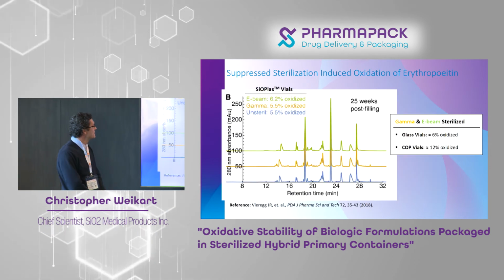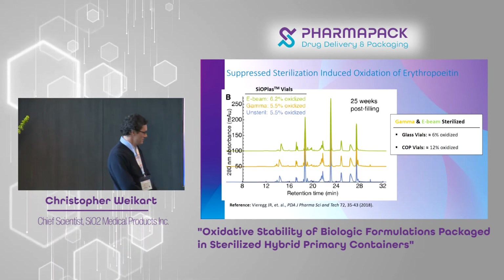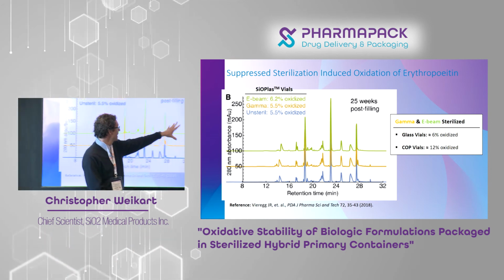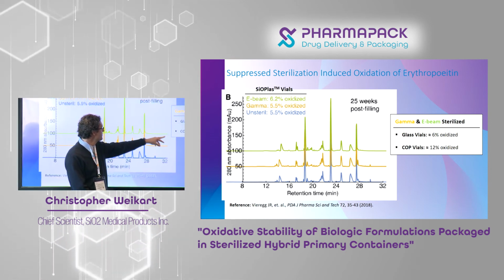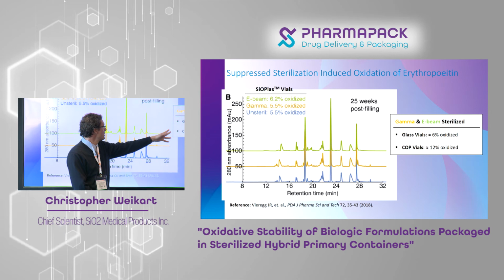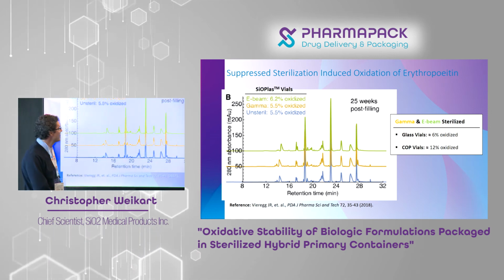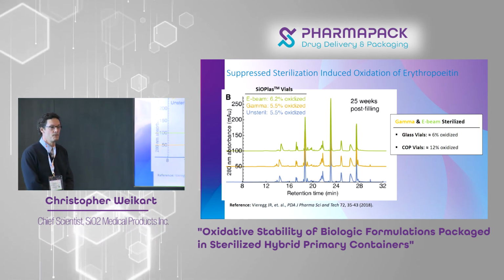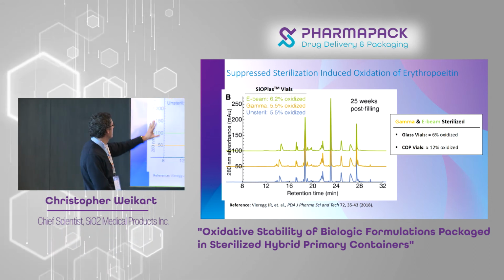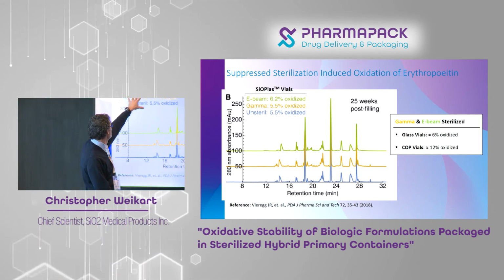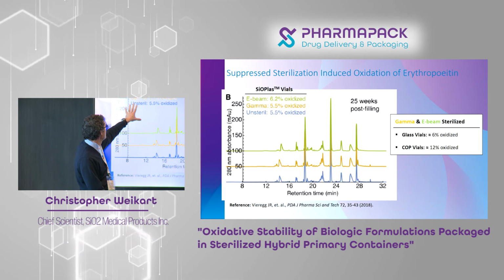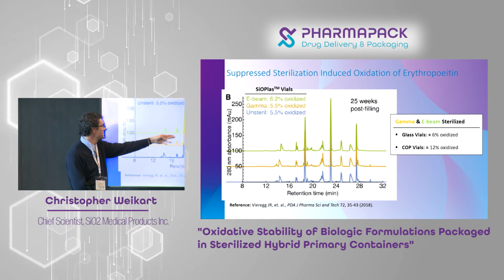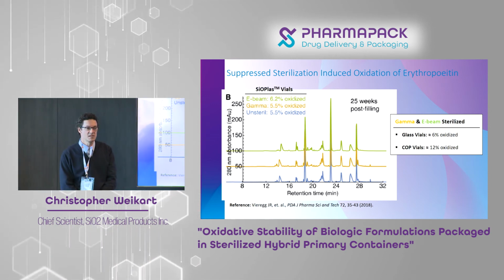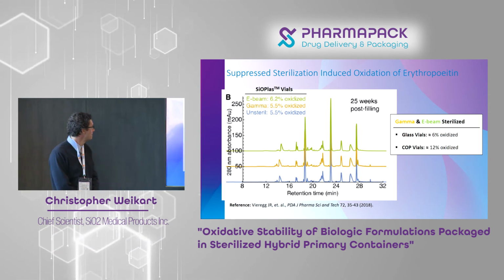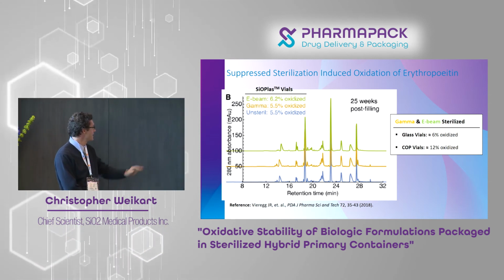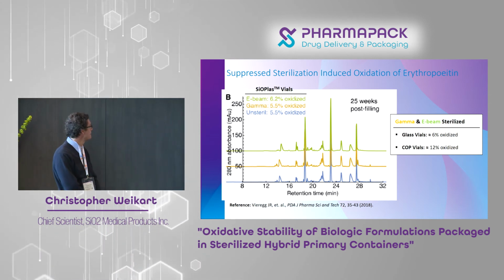And then erythropoietin, in this case, you can see percent oxidation of gamma and E-beam sterilized vials in COP. So COP alone, about 12%, so about double that of what you'd find in a glass vial. And then compare that to our vials, E-beam and gamma sterilized, and again, you can see about 6%, so very similar to a glass vial by comparison. And again, this was after 25 weeks.